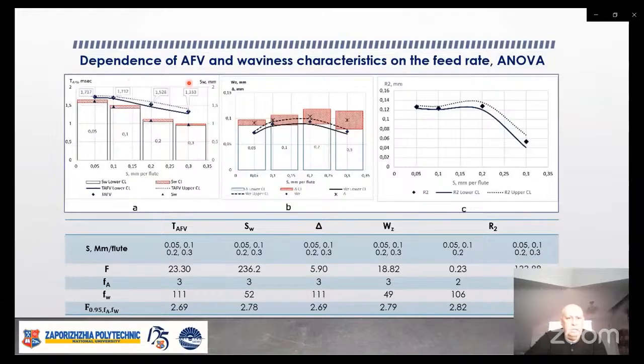Let's see the dependence of AFV and waviness characteristics on the feed rate as well as their statistical significance. Figure A shows the dependence of the AFV period and the pitch of waviness S sub W on the feed rate. We see that these two dependencies have a similar character. Figure B shows the dependence of W sub Z, the height of waviness, and delta, the deviation of the first wave, on the feed rate. These dependencies also have a similar character, and this dependence is statistically significant as well.